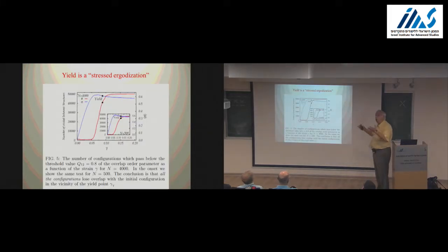How do I know that all of them separate? I can count. So I told you we have 500 configurations in each patch. I have 100 patches, so I have 50,000 configurations, and I'm just measuring. So this is, again, the stress versus strain curve. And this is the number of configurations whose Q12 goes below some threshold, 0.8 or something. And you see at this point, whoop, you get a huge increase all the way to 50,000. So all of them separate from each other.